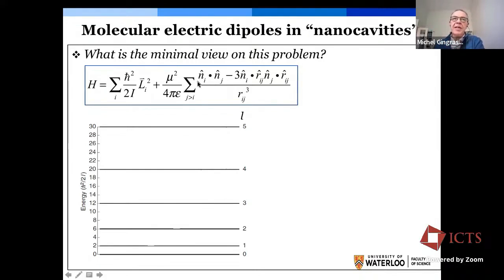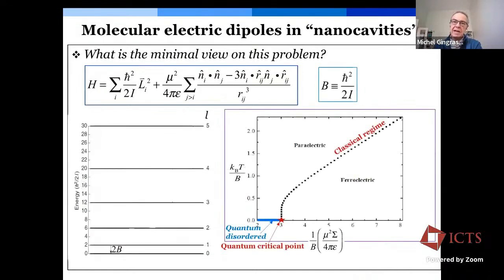Conversely, in the limit where we have very large or very massive particles, classical-like, or very strong dipole interaction, then the minimum energy would be reached at low temperature by extremizing the dipole-dipole interaction. And one would expect to have some kind of phase diagram where we have a regime of dipolar ordered rotors to a regime at small moment of inertia where we have a quantum disordered phase. And so as a cartoon, this is what we expect for the phase diagram. That has not actually been reported, as far as I know, for this kind of system.